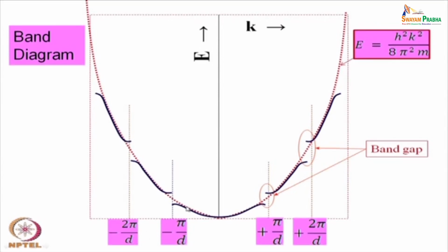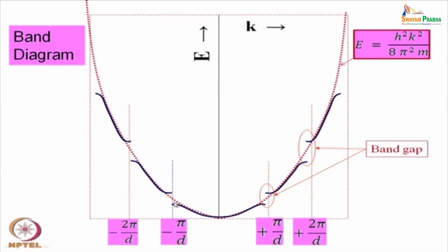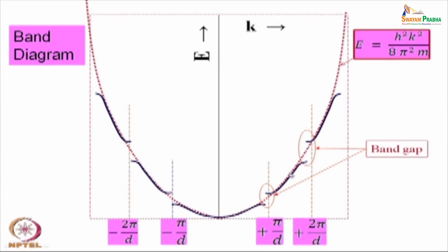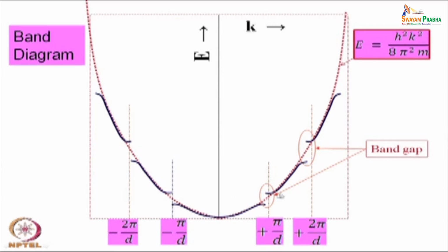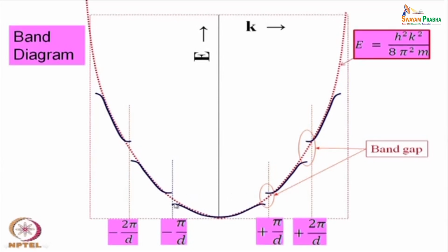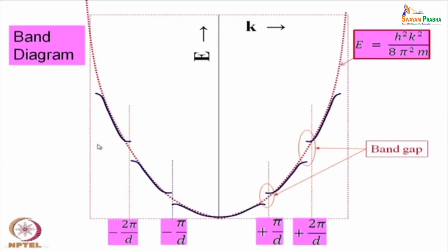But the Brillouin zones are nothing but these bands. Whatever you are seeing in the 2 dimensional figure are the bands; these are actually called the Brillouin zones. Now, there is a consequence of the complexity of these geometric figures. These bands or band gaps, these energy levels, are not uniform throughout; they are different in different directions, along the different axes. Although in a particular section we found that they are quite symmetrical, they are really not symmetrical.